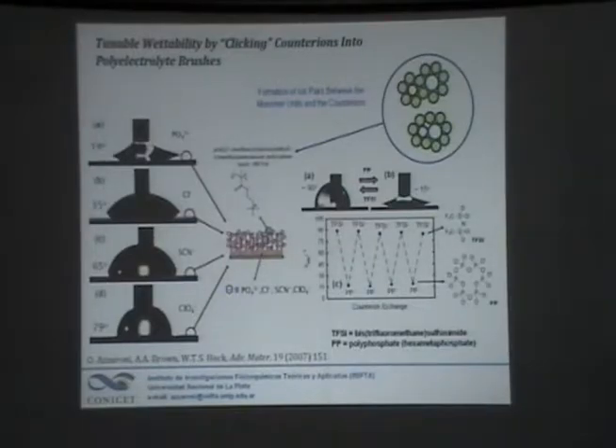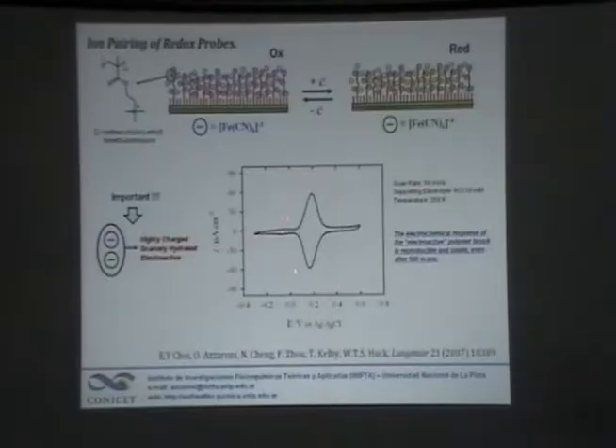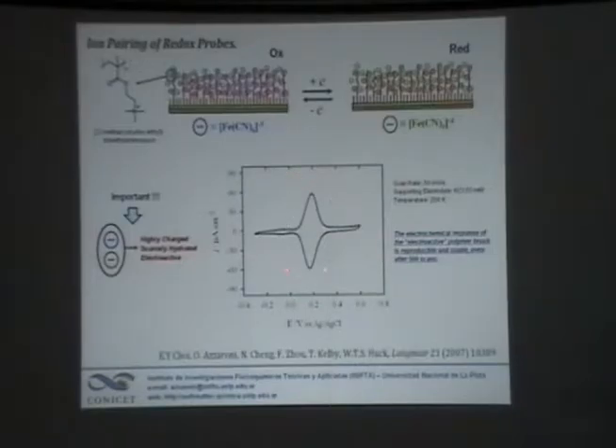The polymer brush works like a simple versatile platform for doing chemistry on the surface. In a similar way, you can create ion pairs with redox-active species — ions which are able to oxidize and reduce — conferring electroactive properties to that surface. Simply put the substrate for five to ten minutes in a liquid solution of, for example, ferricyanide, which is an electroactive ion, then scan the potential in the electrochemical cell and you will observe the redox response of the electroactive counter-ions inside the film.